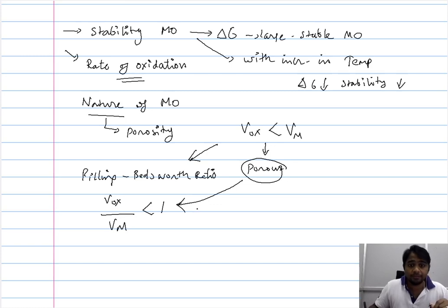Again, this depends on the nature of the metal. When you have a significant amount of metal reacting with a small amount of oxygen, you have the formation of porous metal oxide. And that is what is being expressed in numerical terms by considering the Pilling-Bedworth ratio.